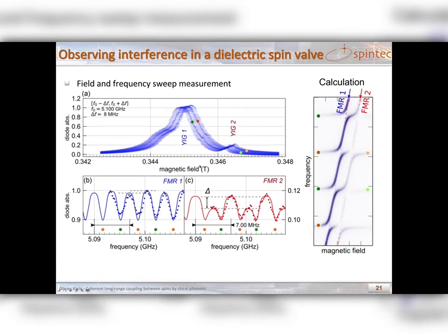Now experimentally we can verify this. We sweep here the magnetic field and then overlay the sweep at many different frequencies in this plot. Due to the gyromagnetic ratio, the spectrum shifts slightly, and the shift is different when there is a magnon-phonon coupling, and this creates this dark line. So the even phonon gives stronger intensity, as expected. And this increased contrast shifts sign when you cross the FMR line due to the 180 degree phase shift that you get by crossing the resonance.